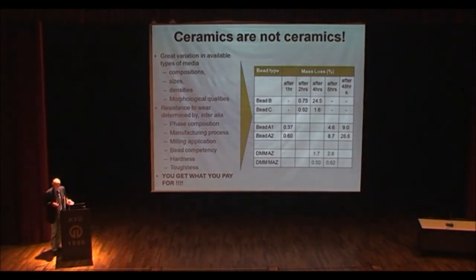That's the outside. You've got to look inside. That bead's going to go through wear. It's going to get slowly smaller. And the moment you start to look inside that shell, you can get down to porosity, to low densities, to a soft media. So you're looking for competency.